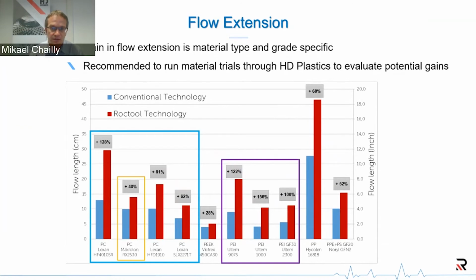And now even if we focus on a single family, the PC1, the blue square on the left side, we can see that even depending on the grades, depending on whatever modification polymer suppliers have made to their materials to fit your requirements, we can have different viscosity behavior. So we can have strong variation of material gain. It is really recommended to run some testing for a given material to evaluate the potential gain in terms of flow lengths for a given grade, and that is something that Roctool can also offer.